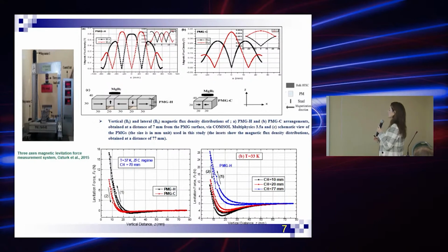And the other figures show the vertical levitation force versus vertical distance at different cooling heights, in a zero field cooled regime at a measurement temperature of 33 Kelvin, and it is clearly seen that when the cooling height increases from 10 millimeter to 77 millimeter, the repulsive force, the positive value, increased, but the attractive force, the negative part, is lower compared to the others, because at this cooling height, the screening current increased, but the trapped field is low.